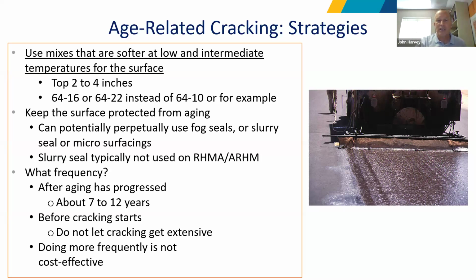This is what your preservation does, your fog seals, your slurry seals, but you need to do those ahead of the cracking. Those are not there really to seal the cracks for very long. Those are there to keep from aging and slow down the aging process. So what frequency should we be doing those at? After aging has progressed to some degree in a cooler environment with softer materials, you don't have to do it as quickly, but in other places, hotter places, you have to go more quickly. But you want to do this before the cracking has gotten too extensive.